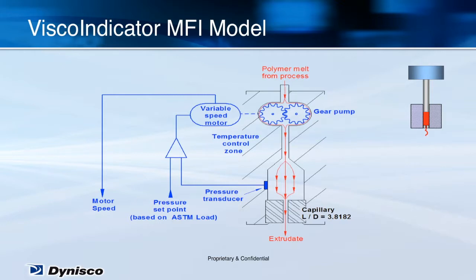The visco indicator simulates both the apparatus and test conditions of the melt flow index test right on an extruder. In the model of the visco indicator you can see on this slide, a side stream is taken from the extruder as indicated by the red text at the top center. Process pressure from the extruder forces polymer melt into a metering gear pump. The pump then generates the flow rate and pressure to extrude the polymer through a capillary.